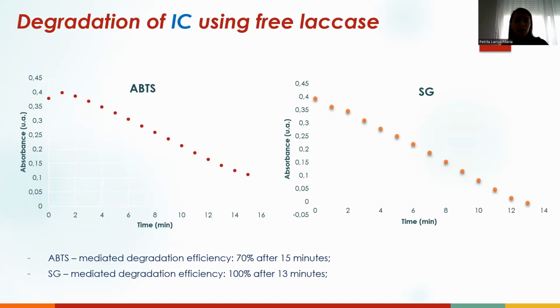Next, we studied the degradation of indigo carmine, firstly in the presence of free laccase, using ABTS or syringaldehyde as mediator. We observed that when using ABTS as a mediator, the degradation efficiency reached 70% after 15 minutes, while when using syringaldehyde, we obtained a 100% discoloration efficiency after 13 minutes, results that confirm that the pair laccase-mediator can be used for the degradation of indigo carmine.